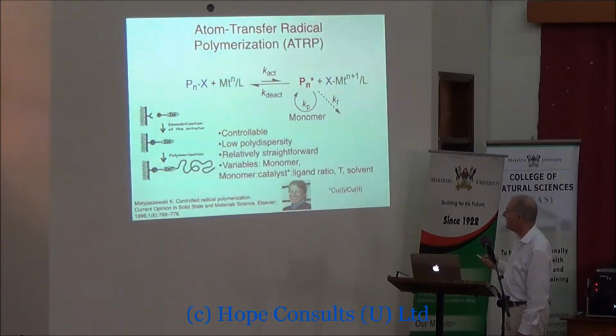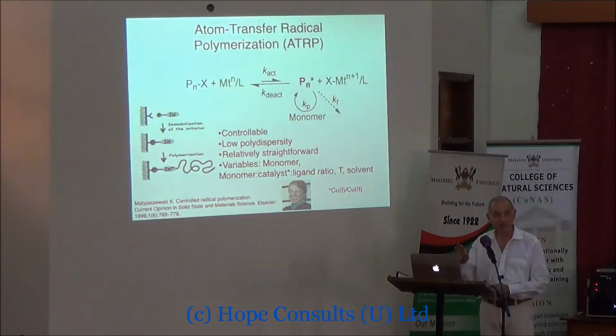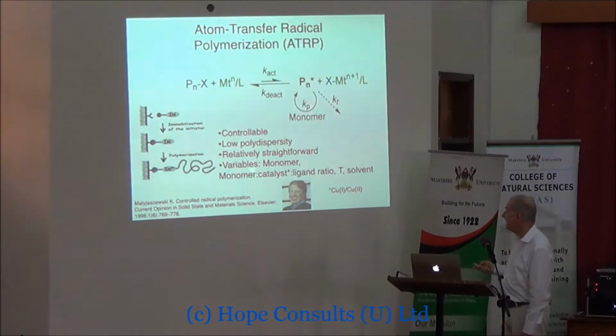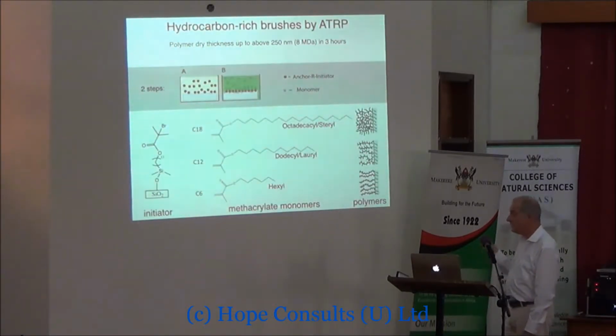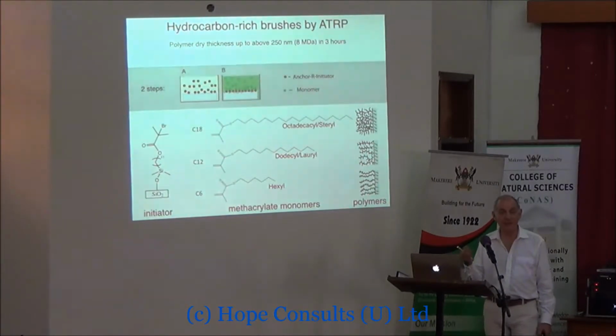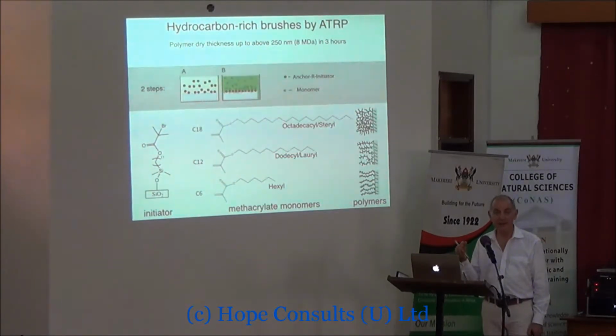And the important thing about it, don't worry about the chemistry for now, is that it's very controllable and leads to very low polydispersity, which means all the chains have the same length, which is what we want. And it's relatively straightforward to do on the surface. So we immobilize our initiator, and then we do the polymerization reaction and grow the chains out from the surface. And we wanted these chains to be oil compatible, so they had to be soluble in hydrocarbons, like motor oil.